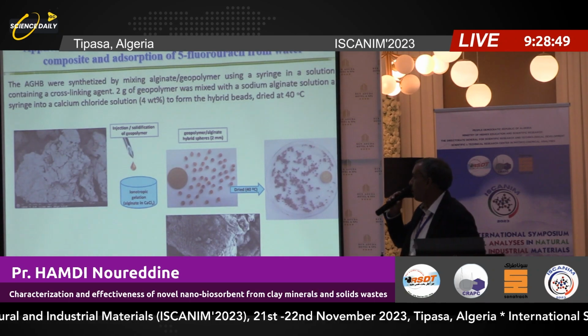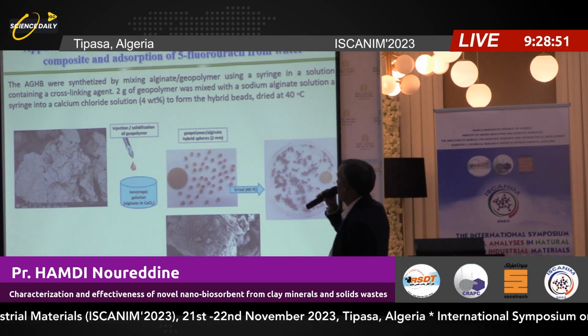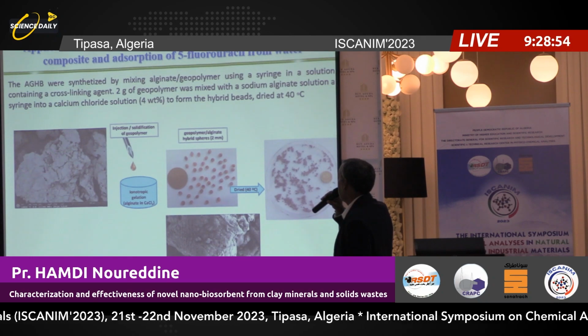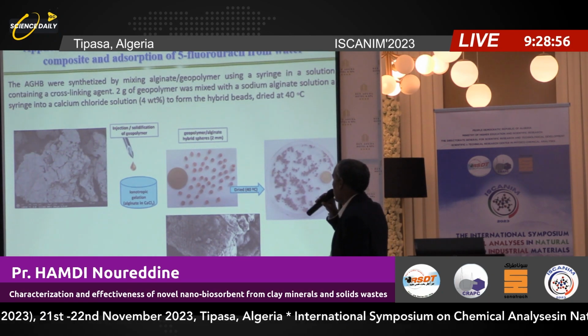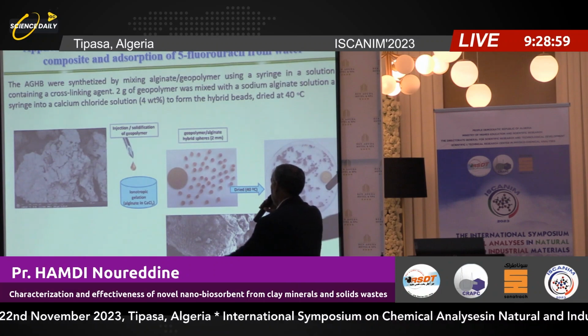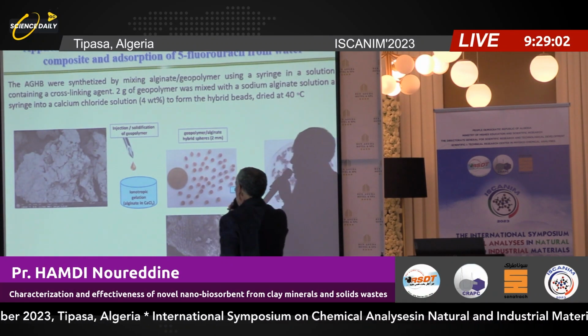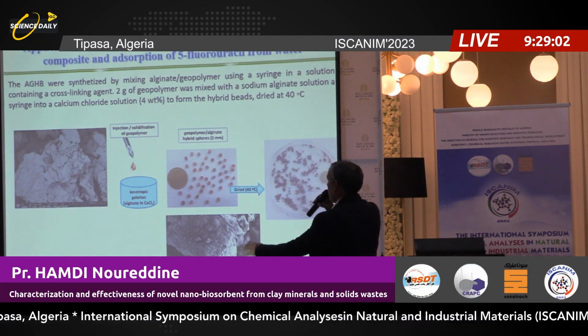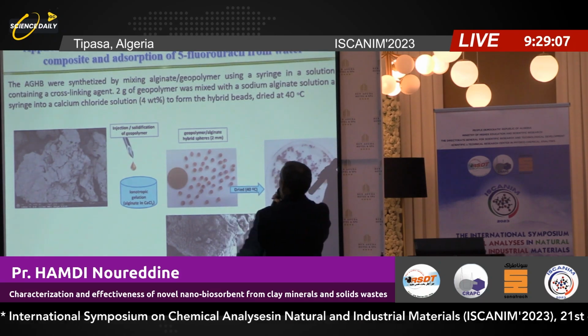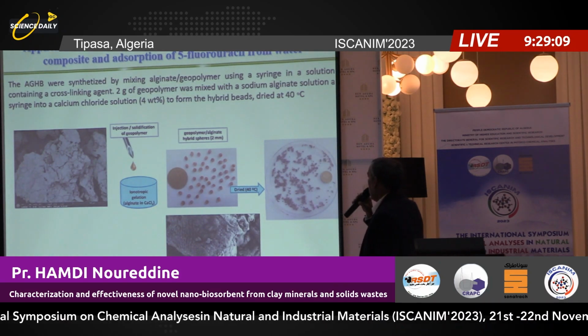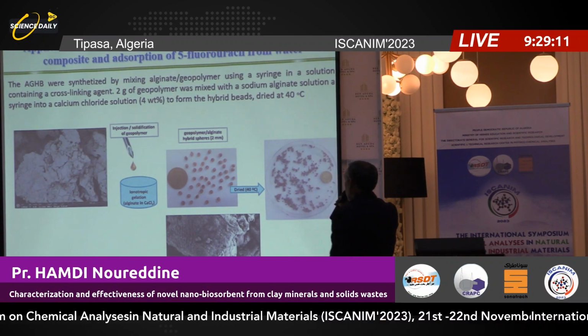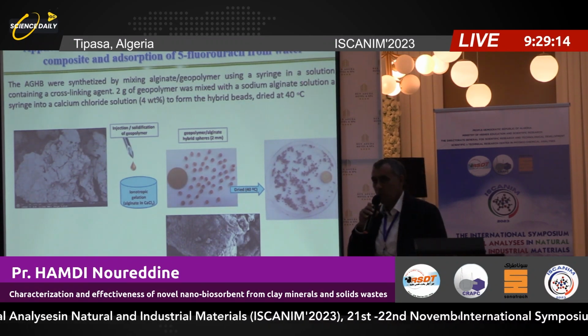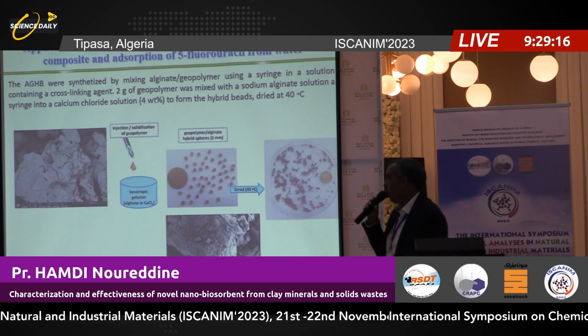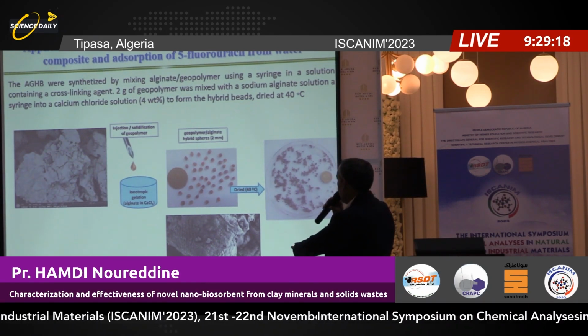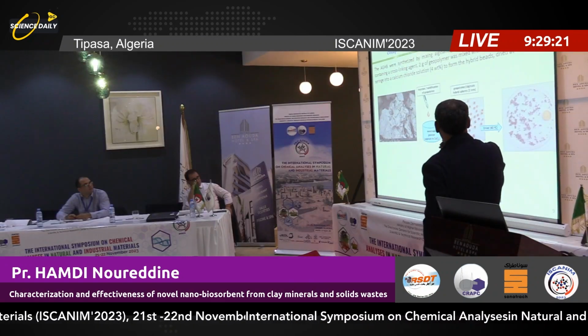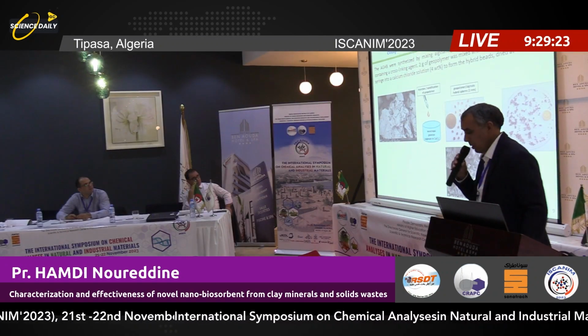Now, the second application is the synthesis of the composite alginate geopolymer, using a syringe with alginate and calcium chloride in order to obtain small spheres of 2 millimeters diameter, and after that dried at 40 degrees C. You see here the scanning electron microscope photo of the geopolymer, and after that the synthesis of the composite alginate geopolymer.